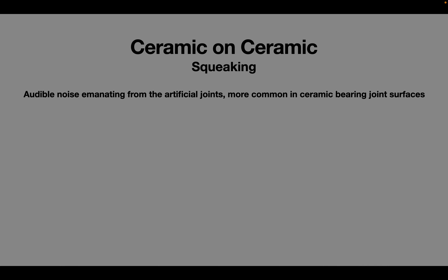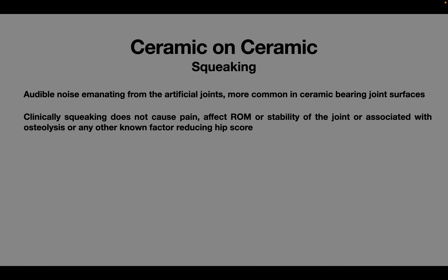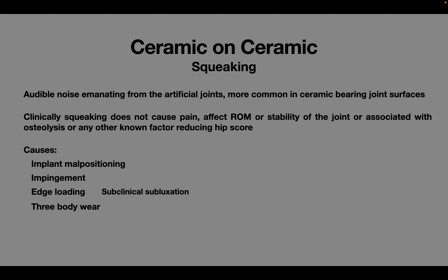Squeaking is an audible noise emanating from artificial joints, especially with ceramic implants. It is more common in ceramic on ceramic compared to ceramic on polyethylene. Clinically, it does not cause pain, reduced range of movement, or any other functional disabilities, and is not known to be associated with osteolysis or soft tissue complications. However, it can be a nuisance and some patients seek treatment. The exact cause of squeaking is still not known. Possible contributors include malpositioning — especially increased acetabular abduction angle — impingement, edge loading, subclinical subluxation, and three-body wear. Implant resonance with contribution from stem alloy materials could also amplify the noise and create squeaking.